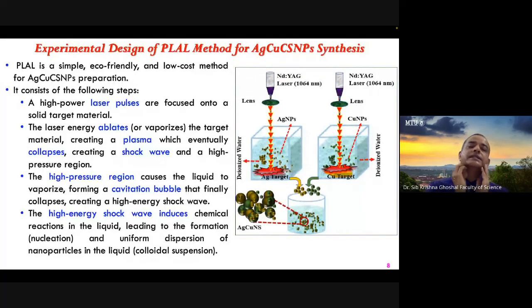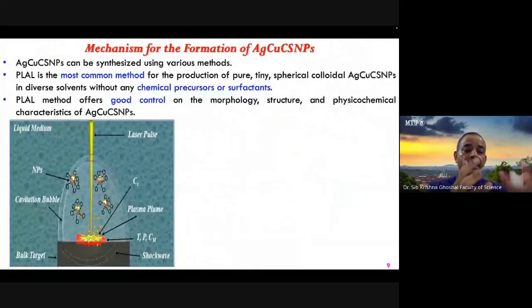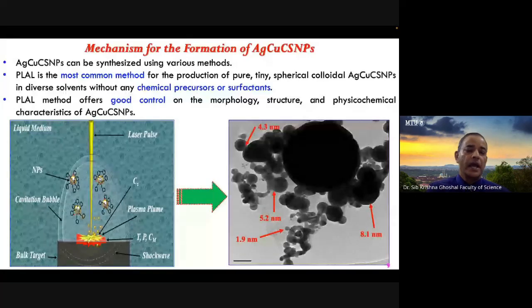So if we use this kind of laser and ablate the target with the pulse, then it will create inside the liquid a high pressure region, a cavitation bubble. Then a shock energy wave will be induced, they will burst, then thermodynamic equilibrium, statistical equilibrium will finally bring the nanoparticles in the solution. And here is the mechanism of how the cavitation bubbles are formed the moment the laser pulse hits the target material, whether it is silver, gold, or any other target. And then finally, we take this liquid sample where the nanoparticles are suspended.